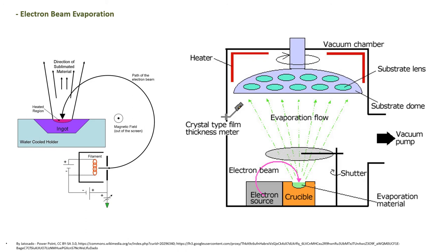The main disadvantages, however, is that electron beam physical vapor deposition is a line of sight deposition process when performed at a low enough pressure, roughly lower than 10⁻⁴ torr. The translational and rotational motion of the shaft helps for coating the outer surface of complex geometries, but this process cannot be used to coat the inner surface of complex geometries. Another potential problem is that filament degradation in the electron gun results in a non-uniform evaporation rate.